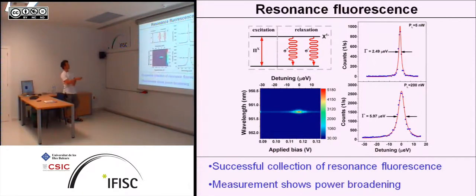And there we can now directly go to an experiment. So here we excite the x1 minus state. We use x1 minus for some other reasons. So in principle this is also applicable to hole spins. So you just excite it with linearly polarized light, and then the relaxation photons will be circular polarized, so sigma plus and sigma minus. And then we will always collect 50% of either one.